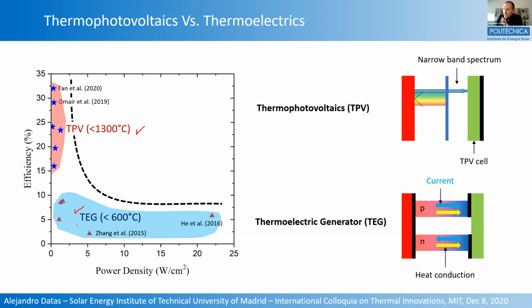But we could say that thermionics will lie more or less where thermoelectrics technology is represented in this figure, with the difference that thermionics typically operate at extreme temperatures much higher than 1000 degrees Celsius. But in general, you can see that thermophotovoltaics performs very well in efficiency. You have here these two recent results that Andrej just commented on, with efficiencies already over 30%. And thermionics or thermoelectrics as well perform very well in power density, but not as good in conversion efficiency.